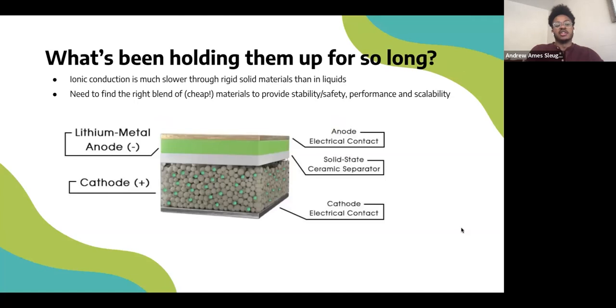The main challenges that arise with solid-state batteries are regarding the material selection. You need electrode materials with high energy capacities and reasonable volume expansion during cycling so that your battery isn't exposed to high mechanical stresses. You also need an electrolyte material that is chemically inert at the interfaces with the aforementioned electrodes with a high ionic conductivity. Ion conduction is much more difficult within a solid material than it is in a liquid electrolyte because the processes of diffusion are much slower, which AK will talk about later.